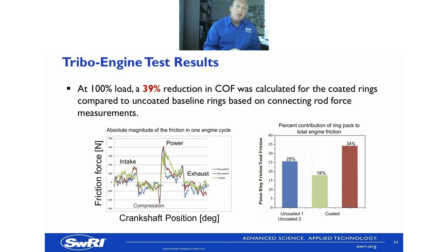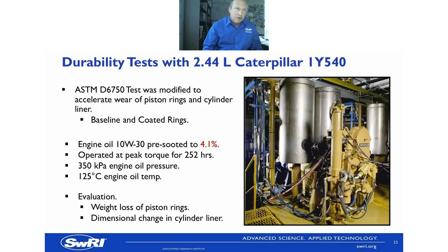On the right-hand side, you can see we built the engine and we ran it with the standard rings. We then put in the coated rings we'd developed, and then we ran again with the standard rings, and on average we saw a 39% reduction in coefficient of friction. Obviously you're not going to see that in an engine. No, it's a little bit biased in the single cylinder Hydra engine because you haven't got as much stuff as you have on the full size engine, but it still points in the right direction of the effect that we have.